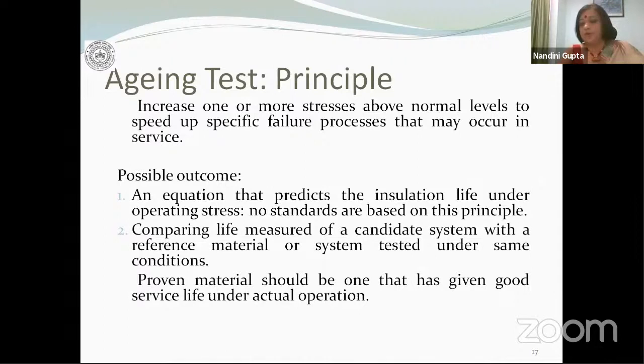Now, when you're performing a breakdown test, it is very easy to figure out when the test has passed or when the test has failed. If puncture occurs, it has failed. If no puncture occurs, it has passed. But that is not going to work with aging, because in aging, we are looking at degradation. We are not necessarily looking at catastrophic failure. So once you perform the aging test, what you will get at the end of the day is preferably an equation which predicts the insulation life under operating stress. That means you will be able to do a statistical analysis.